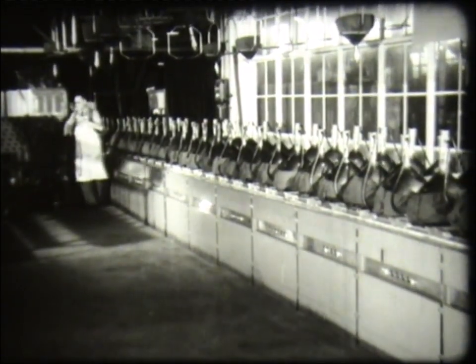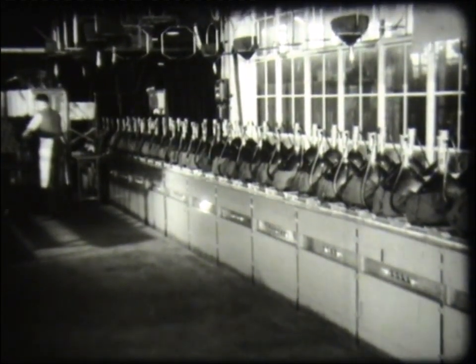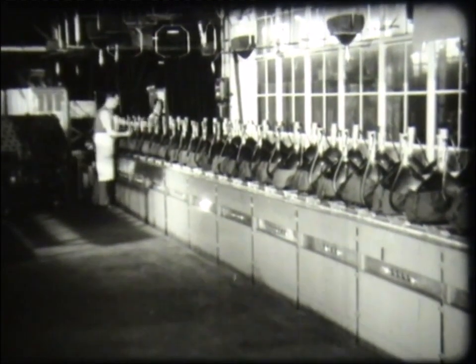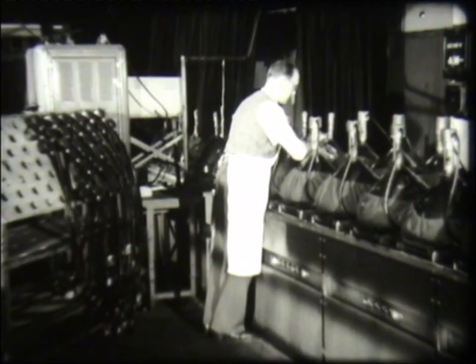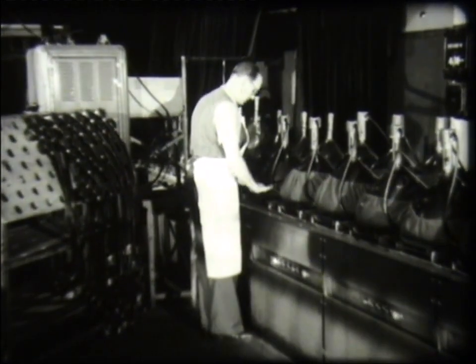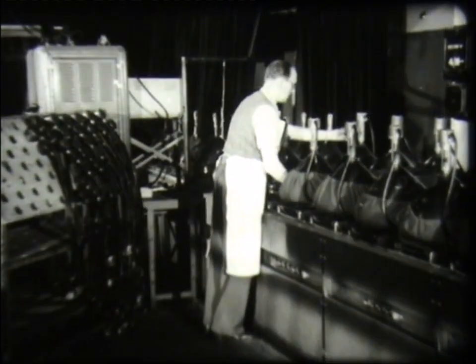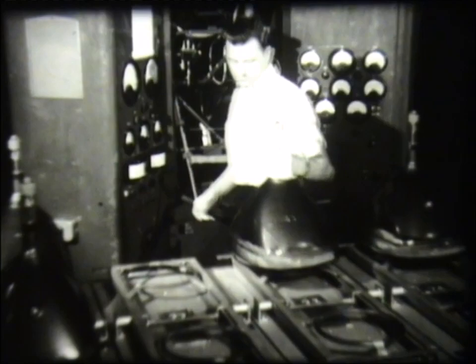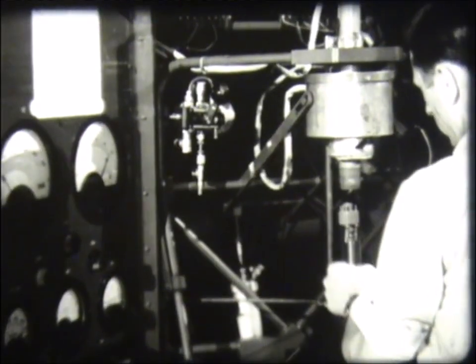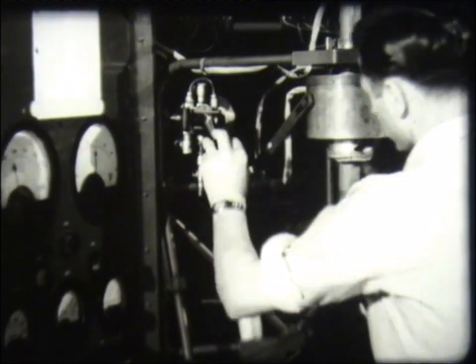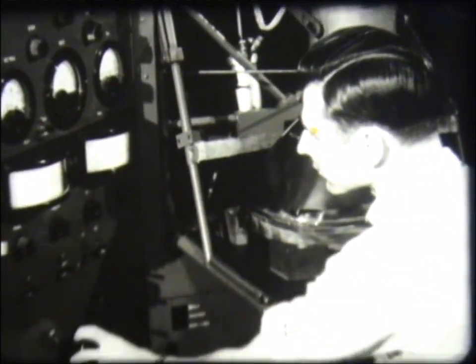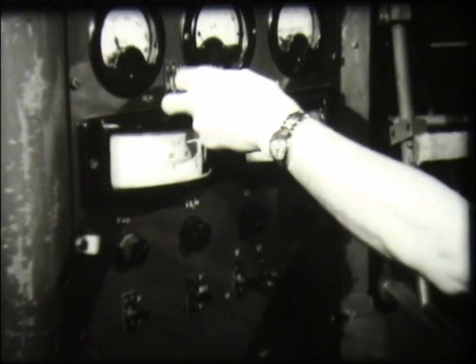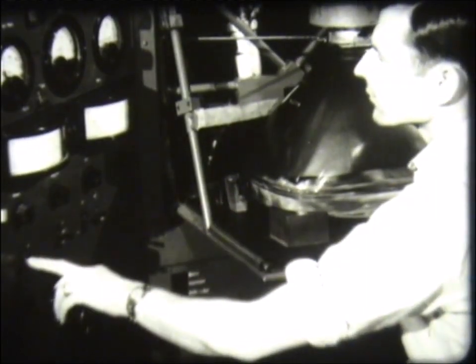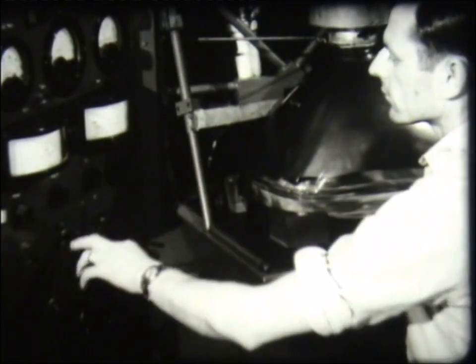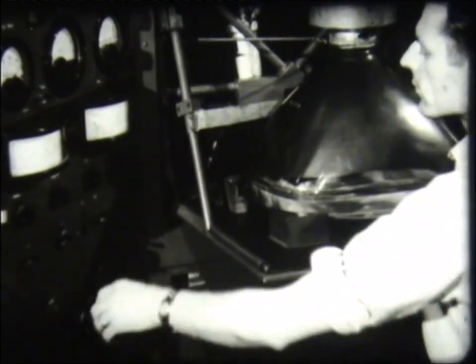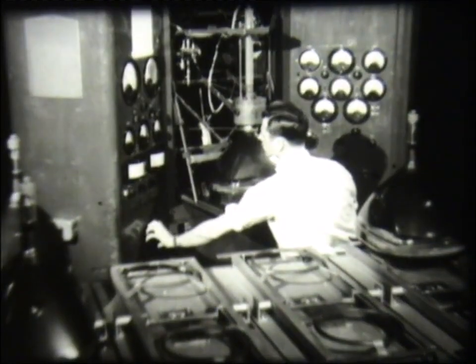During its travel, the tube is also aged by operating it under controlled conditions. This causes other chemical changes in the cathode material, which result in improved emission. After aging, the tubes undergo a series of severe tests laid down by the Quality Control Department, and every tube must pass all of these tests. They include tests on insulation resistance between the electrodes, vacuum, heater current, evenness of illumination and color behavior at overvoltage, point of cutoff, and uniformity of cathode emission.